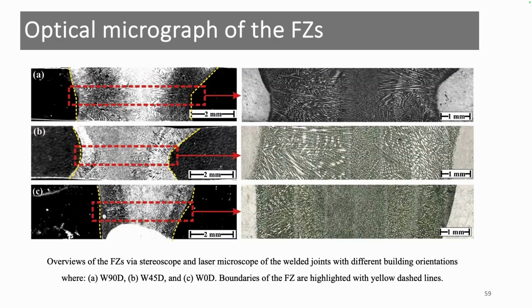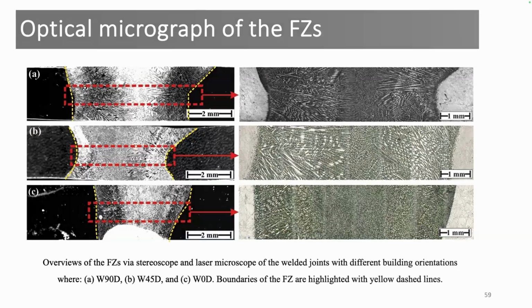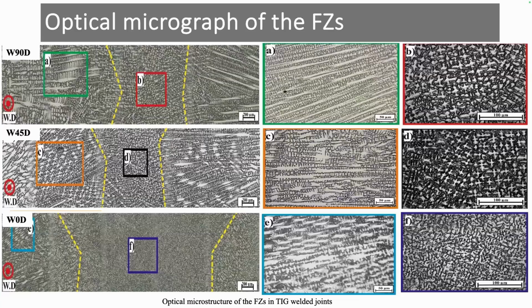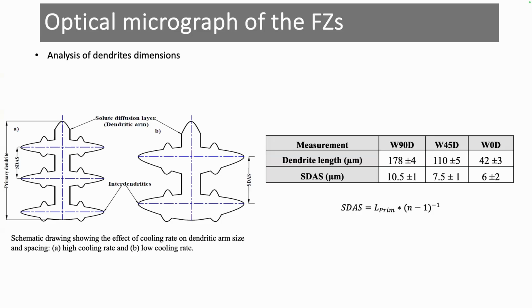Furthermore, the size also of the grains here in the 90 degree, the size of the grains or the structure here was greater than that for the 0 degree. Means that there is agreement between the cooling rate in TIG and laser welding joints. And here we made some zoom on this structure at the fusion zone for this 90-degree, we find that the size here of the dendrite arms are greater than that for the 0-degree. And the main reason also is cooling rate.